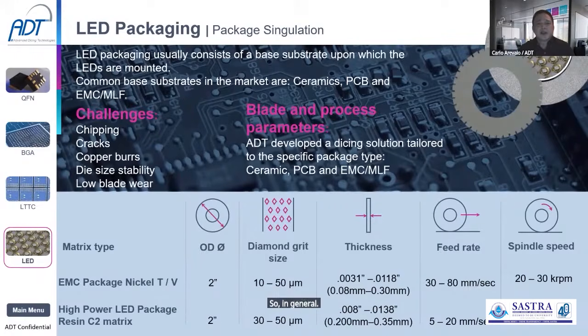So in general, for this particular packaging, the recommendation or the process could either use a hard nickel blade when you are using a soft base substrate, or you could use a soft resin blade if the substrate is a hard base substrate. For the 2-inch nickel blade, your grit size would range from 10 to 50 micron with 80 to 300 micron of thickness. Feed rate is relatively not as slow, because it could go as fast as 80. So the range can be from 30 to 80 depending on the thickness of the substrate. Spindle speed would range from 20 to 30.